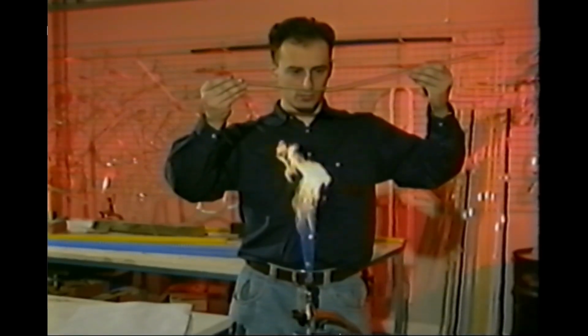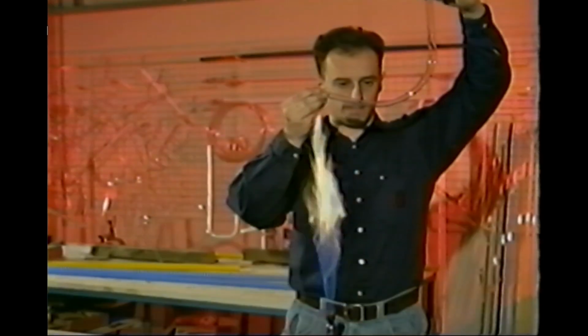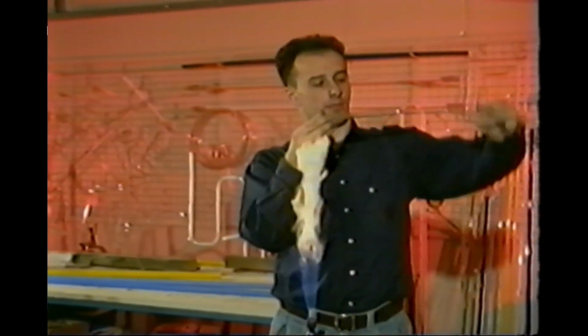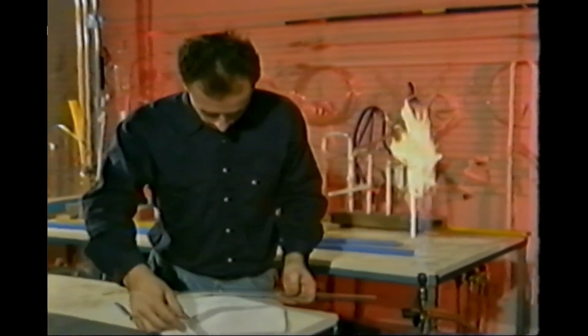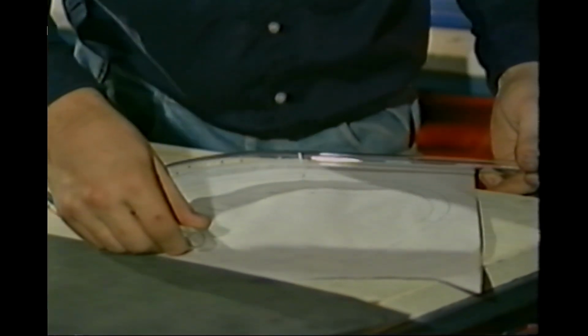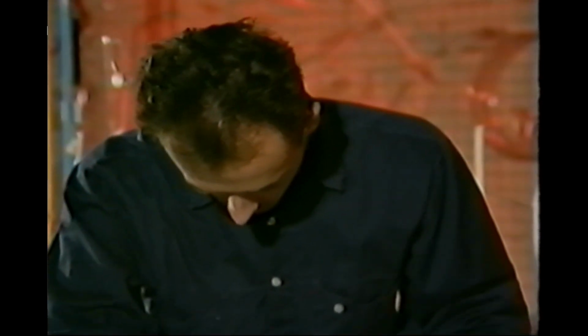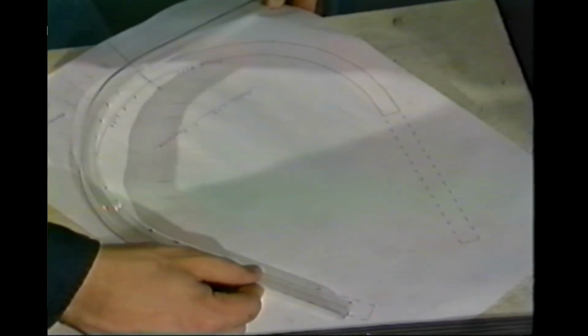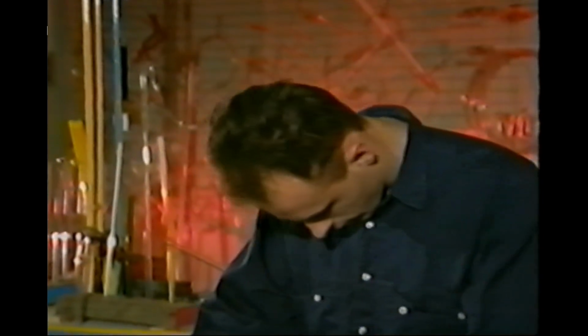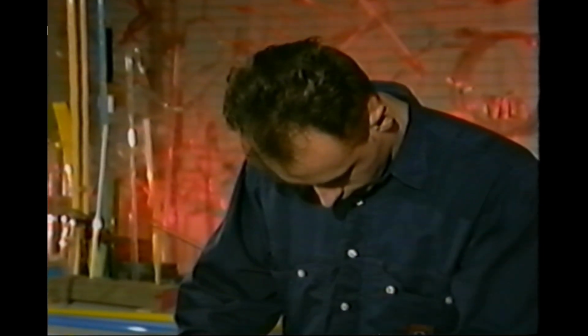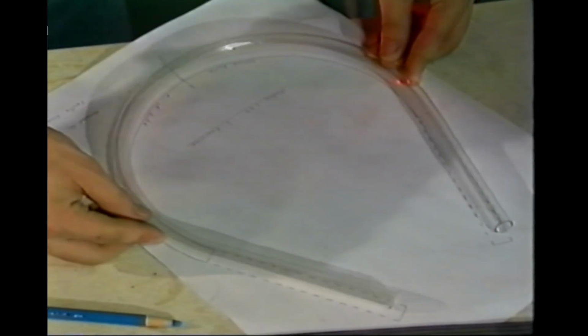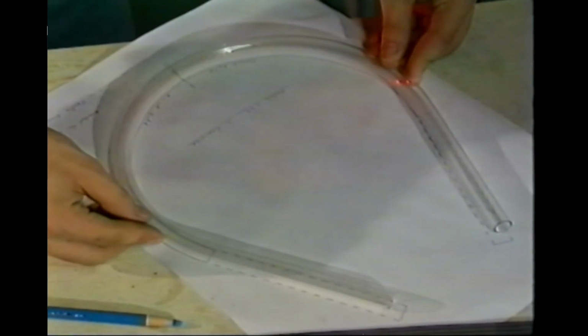Continue this bending, checking and marking process until the first side of the letter C is complete. If the tube has been fitted to the drawing and marked and bent correctly, an exact fitting gentle curve will be achieved, with all the marks equidistant from each other. If the alignment and straightening after each melt has been performed correctly, the half curve will be flat when laid on the bench. The second side of the letter can now be bent, using the same process, always checking that the first side is fitted to the drawing before checking or marking the next bend on the second side.